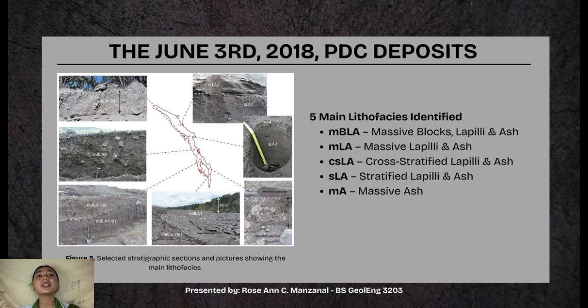To understand how the pyroclastic density currents behave, researchers dug into their internal structure. They identified 5 main lithofacies, or deposit types, based on characteristics like grain size, layering, and composition. The valley-confined deposits were thick, sometimes over 20 meters, and filled with large boulders. These layers often showed aligned clasts and color changes caused by oxidation, giving clues about the sequence of flows, with later ones being more oxidized.